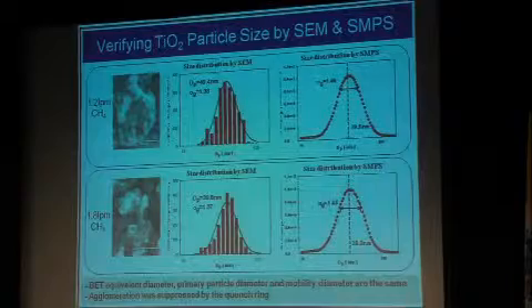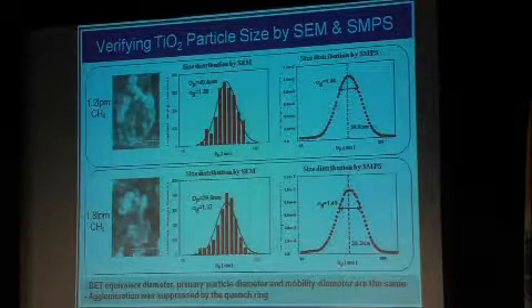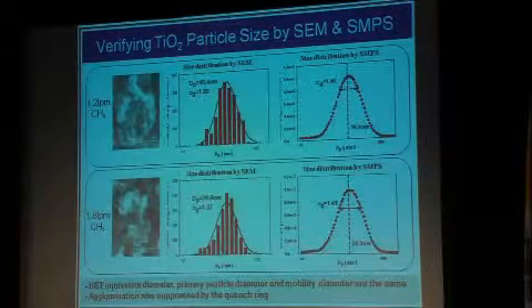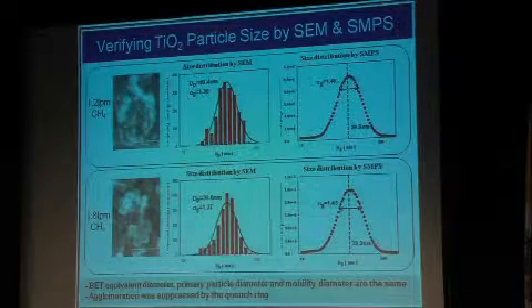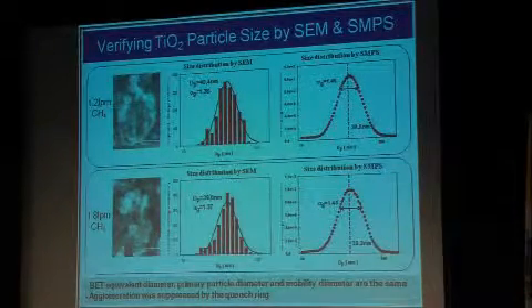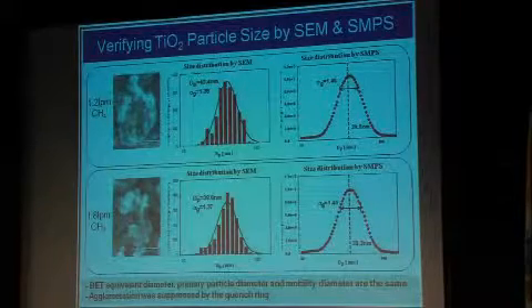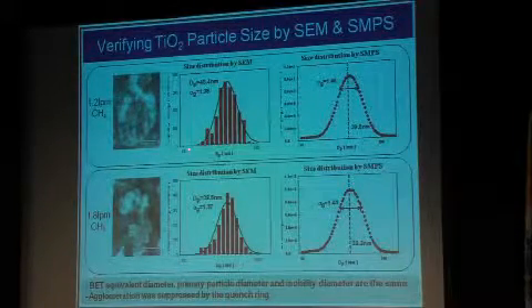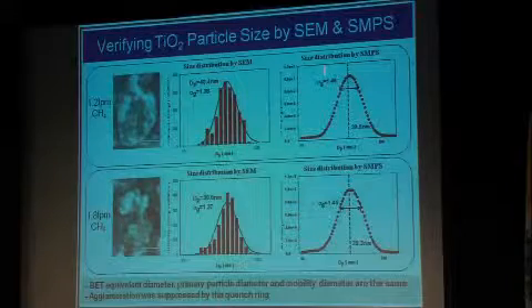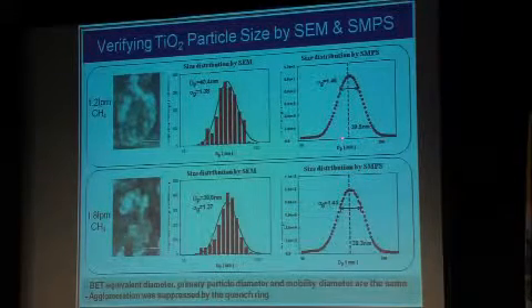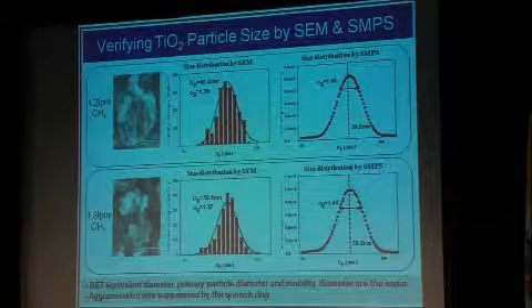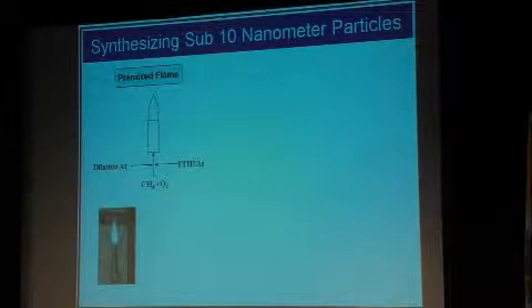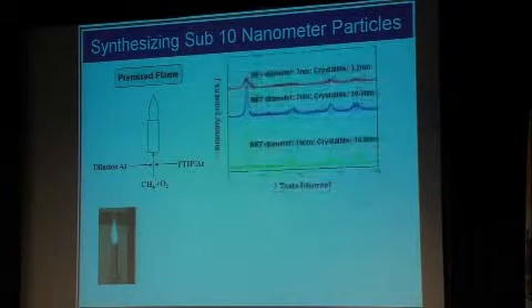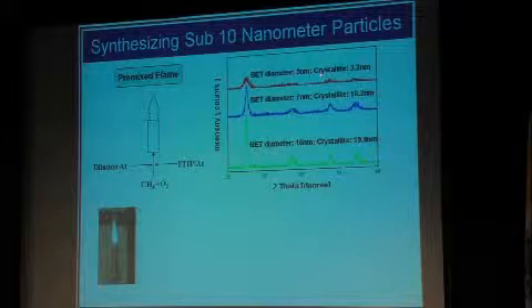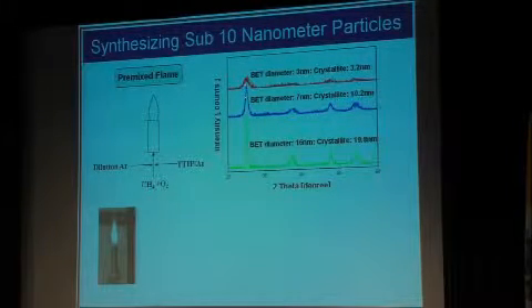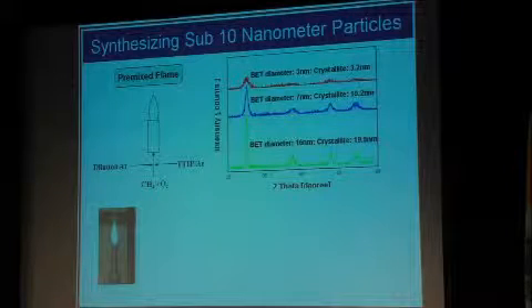These are measured by electron microscopy, but I also have my online tool, and they tend to agree quite well. And these are, of course, a natural spread that I obtain for a given experiment. And I may not be happy with this relatively broad distribution. In some sense, it's quite narrow in terms of the width, but I might want tighter control, and I might want smaller particle sizes. And you can see that the crystal phase, you can also determine it by X-ray diffraction. You can determine the crystal phase.